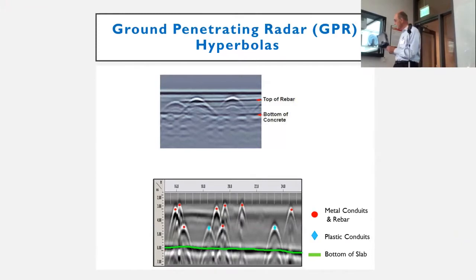and the cart picks up an image. And the way it does it is it sends a signal from one side of the cart into the concrete or whatever the material is, and then that comes back. And it's the dielectric constant of the material that we're looking at that really tells us what it is. But the basic principle is that we generate a set of hyperbolas. So in the top, just looking at the top graph here, this is a cross-section through a slab. This shows the top of the slab. This hyperbola, which shows the intensity of the steel that we just picked up, is because of its maximum. That is where the rebar or the steel is. And then you can see one here, one here, one here, etc.